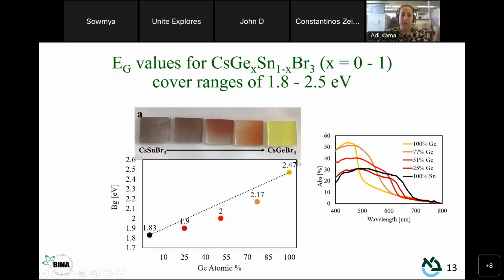So after we established the deposition method, we decided to try to fabricate the 5 different compounds. We sprayed the cesium tin bromide and the cesium germanium bromide and 3 compounds in between with different ratios of germanium and tin. We performed the absorption measurement, optical measurements for the 5 samples.